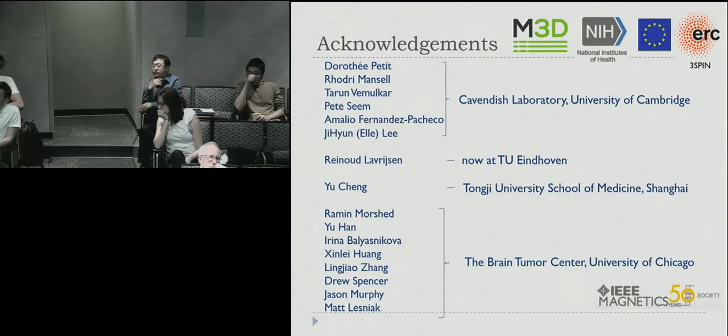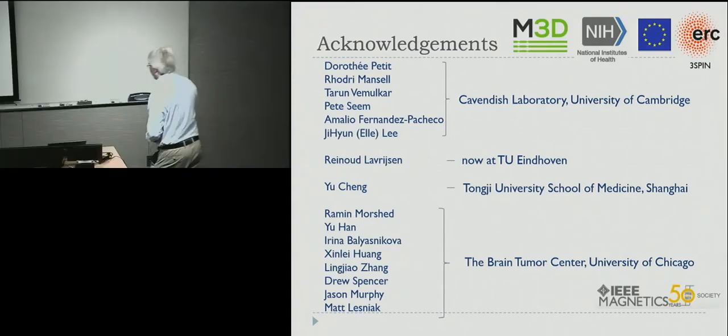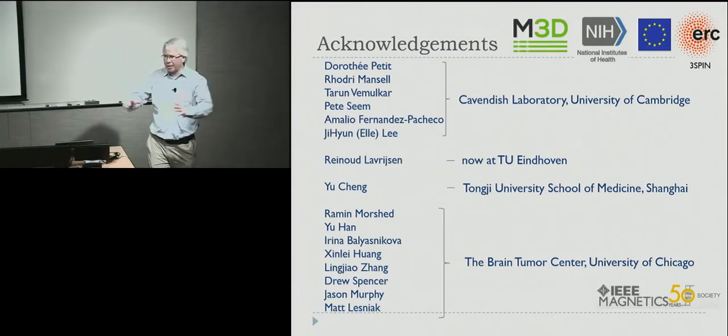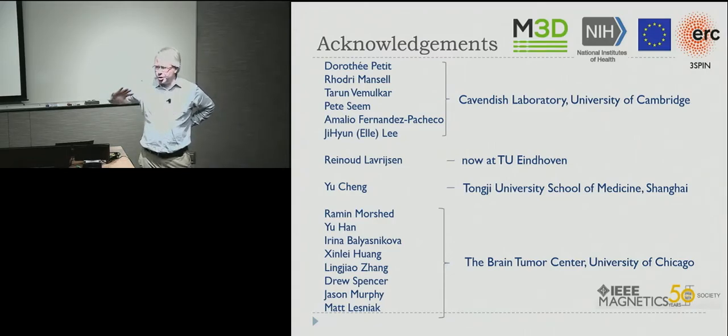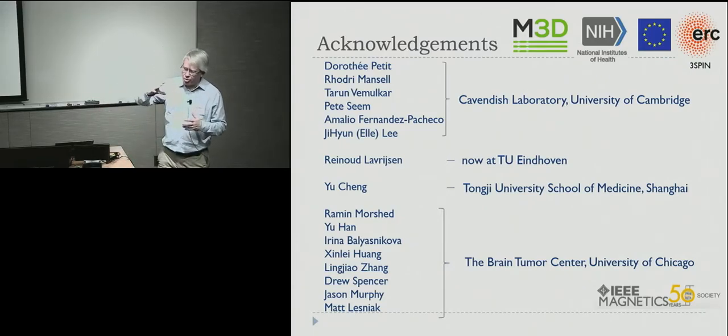That's quite right. We've done a few tests where we begin to structure things down laterally in the memory device. So we've gone from 5 centimeters down to about 200 nanometers. We can get good data down to about 2 microns, because that's the smallest single particle that we can really probe. And you certainly see an upward drift in all the switching fields as you shrink down. But everything moves together. So the operating window just shifts, but you still have the same operating margin. Beneath a couple of microns, we don't have good data as to what happens there, because it's quite difficult to probe in a simple type of device.